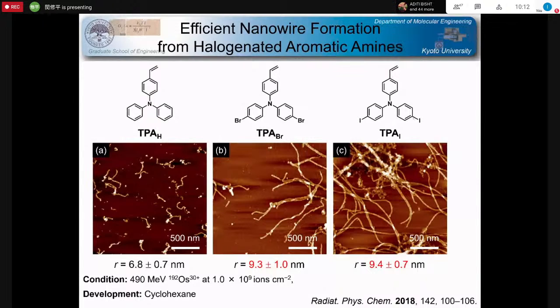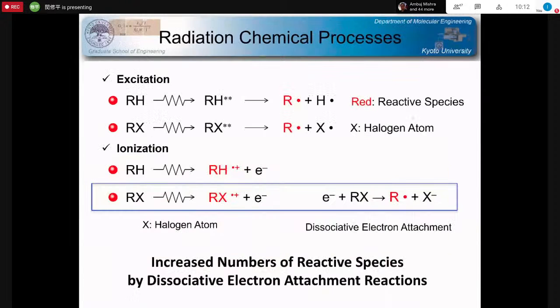And as shown in these three micrographs, unexpectedly, other than the vinyl groups, the halogenation of the organic molecules was more effective to promote the highly efficient chemical reaction caused by the ion beams here. And this is interpreted because,